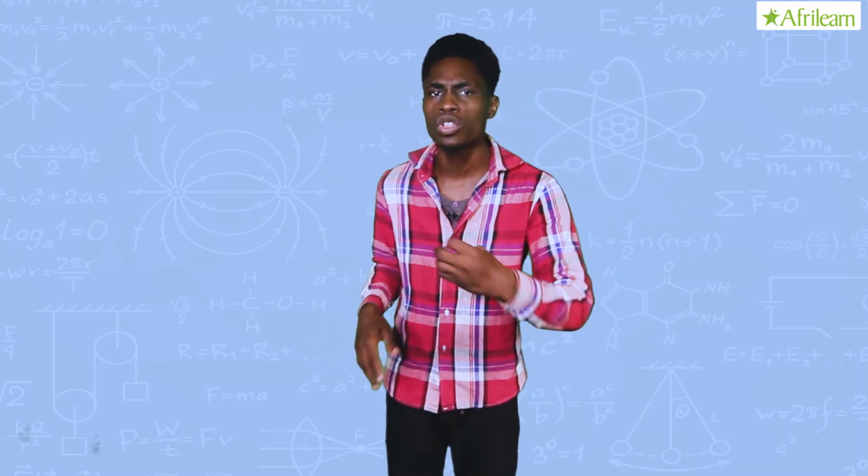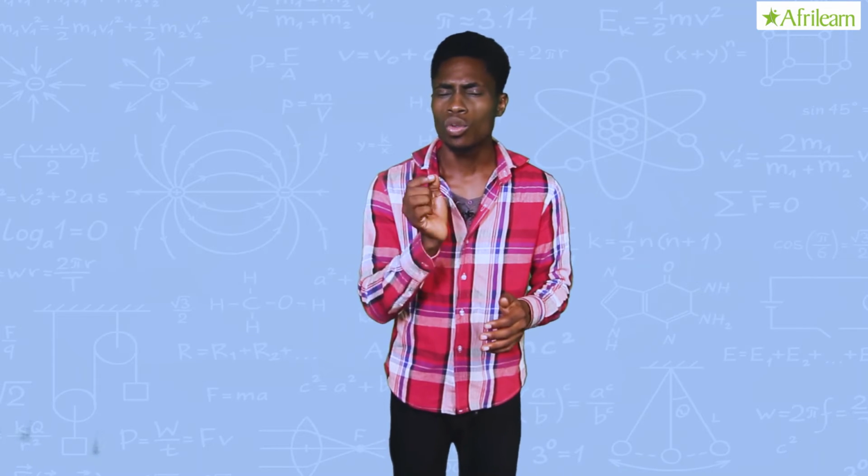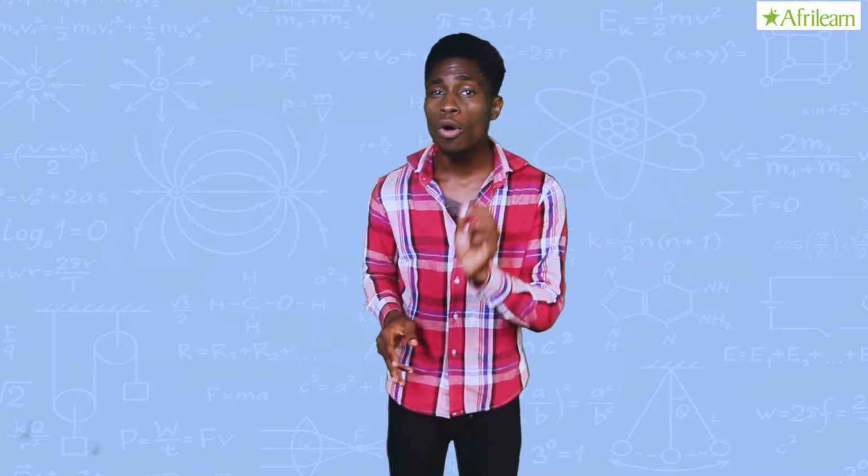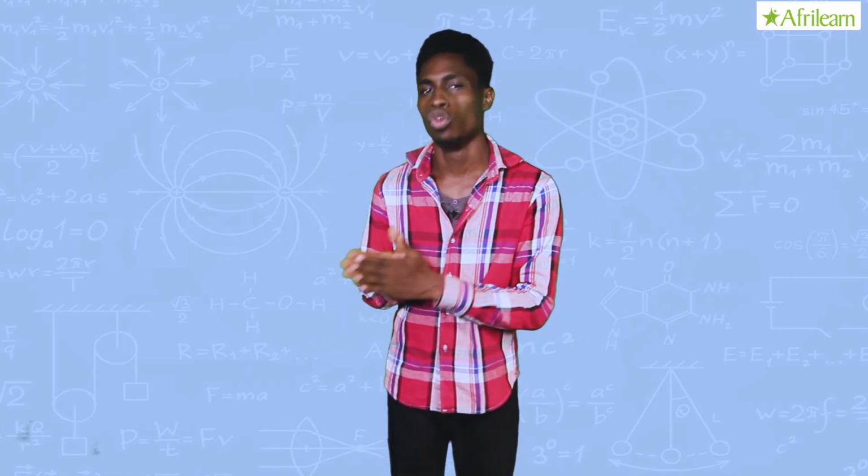The change in specific gravity is brought about because when the cell is discharged, some of the acid is used up in the formation of lead sulfate at the electrode and some water is produced. The proportion of acid to water is therefore lower.